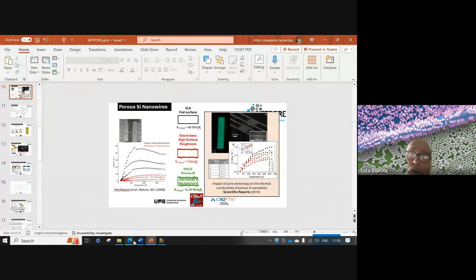And at this point, you can also play with the pores, because you can oxidize and remove in vapor environment without having condensation effects. And so in principle, you can also play with the porosity. I don't recommend to do it on the 100 nanometer wires, because it's very difficult. But you can work on pillars of 1 micron. And at this point, with a thermal oxidation, you can in some way enlarge the pores for sure.